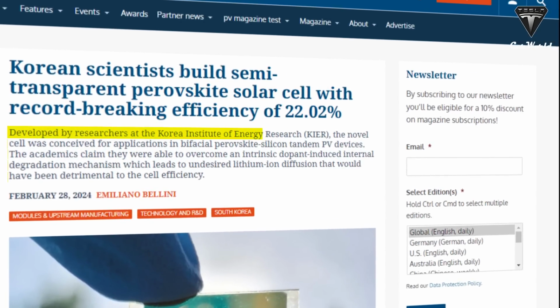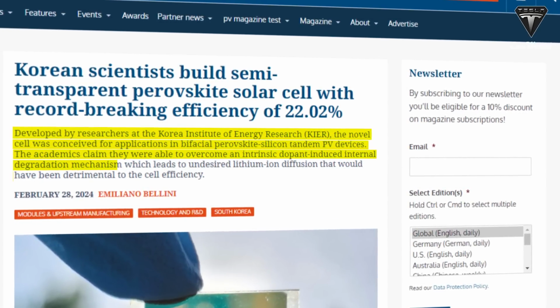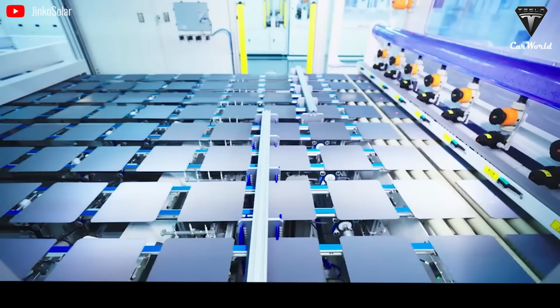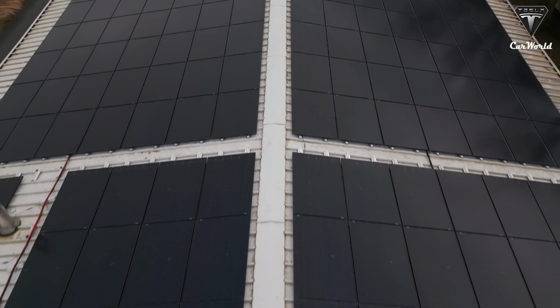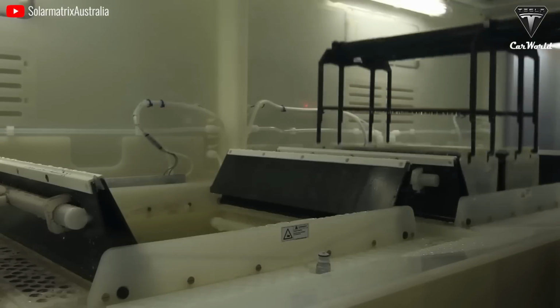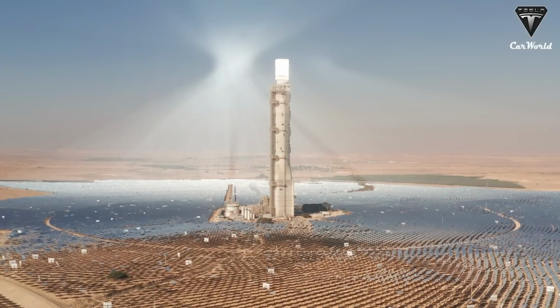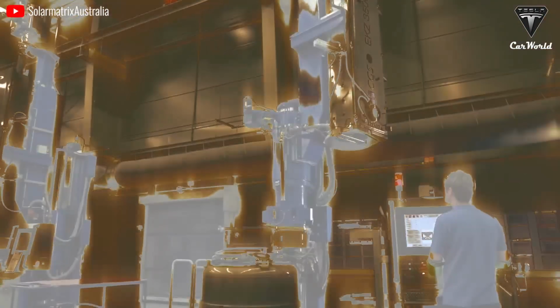Recently, the Korea Institute of Energy Research announced that a group of its researchers has developed a semi-transparent perovskite solar cell intended for applications in bifacial perovskite-silicon tandem PV devices. The academics claim they were able to overcome an intrinsic dopant-induced internal degradation mechanism, which leads to undesired lithium-ion diffusion that would have been detrimental to the cell efficiency.